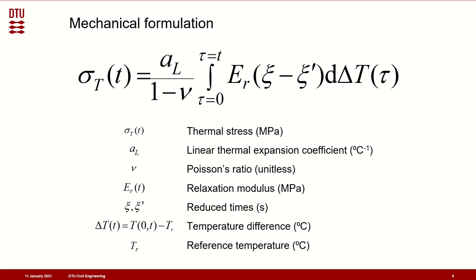The thermomechanical model represents a layered half space which extends to infinity in the x and y directions. With the change in temperature level, this representation does not allow any deformation within any plane perpendicular to the z-axis. Under a change of temperature delta T, this means that the half space does not experience any stress in the z direction and stresses of equal magnitude along any direction within planes perpendicular to the z-axis.